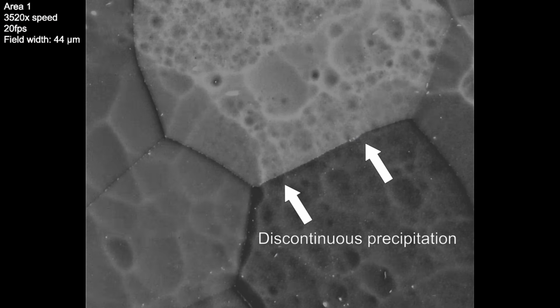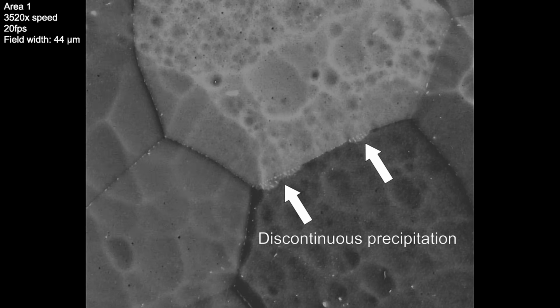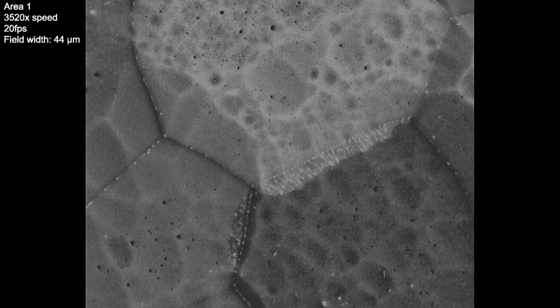Over our 40 hours worth of data collection, consisting of correlative backscatter electron images and EBSD maps, this is some of what we discovered. The continuous precipitation forms first and is incorporated into the discontinuous precipitation as its growth front advances. Second, the discontinuous growth front is pinned by the continuous precipitates for hours at a time, especially when the continuous particle is orientated with its larger dimension perpendicular to the growth front. Third, while pinned, the discontinuous precipitation front needs to gather aluminium solute first to fuel its continued growth. And four, for the discontinuous precipitation to form, neighbouring grains required a misorientation of 10 degrees or more.